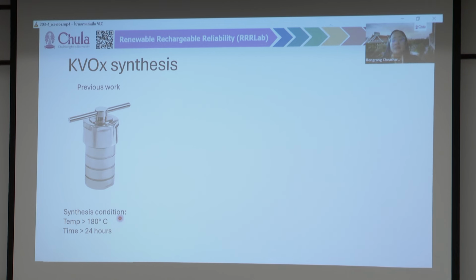Usually, the synthesis takes quite long. The temperature required for this synthesis is above 180 degrees Celsius for more than 24 hours. And after this, you also need to do some calcination to get a good phase.